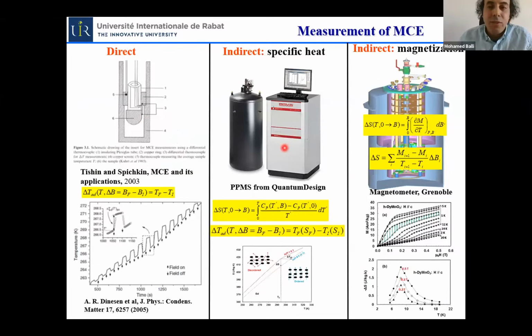However, due to the challenging character of calorimetric measurement, the magnetization method is widely used to determine the magnetocaloric effect, particularly in terms of the entropy change. In this case, all we need is to perform some magnetic isotherms around the ordering point of the materials. Then after, the entropy change can be determined by numerically integrating these isotherms using the Maxwell relation.